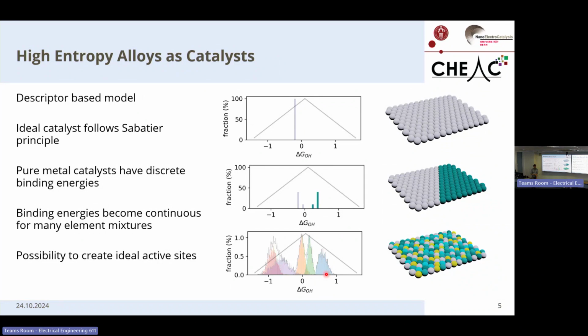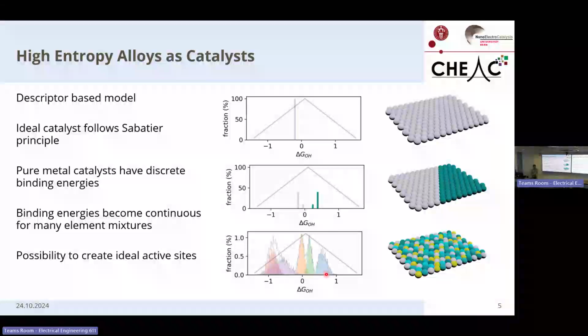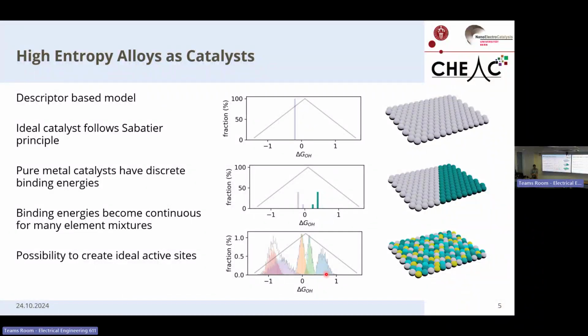Yes. So certainly it depends on the active site, but also because of the stress field on the free surface, as well as inside. Certainly it's trying to reach an equilibrium stress state, and you have more lattice distortion because you have different atomic sizes. That's a lattice distortion not only inside the solid but also on the free surface. Right. And that should increase or decrease the energy necessary for an atom to eject. Yeah, that's something still to study.